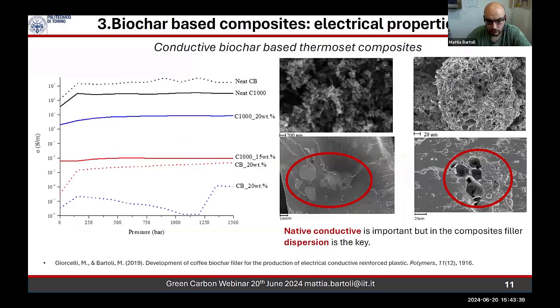Of course, even if the native properties of the materials matter, as you can see here, carbon black and the neat biochar produced from coffee show more or less the same conductivity, even if carbon black is a little bit more performing. Inside the composites, the micrometric structure of biochar is an advantage because of a more homogeneous distribution, while carbon black tends to create islands, and this greatly prevents the conduction.